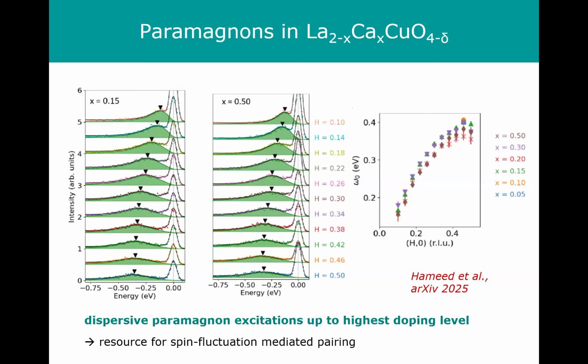Anyway, so these are some of the RIXS data that Sajina Hameed took on these lanthanum calcium copper oxide films. Two different doping levels, optimal doping and highly overdoped. And so these are along one particular direction in momentum space. You don't see very much difference in these spectra. There's slight difference in dispersion relation, but basically these data are similar as far as the dispersion relation is concerned to magnons in undoped lanthanum copper oxide.